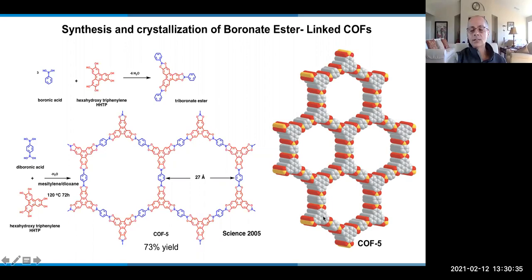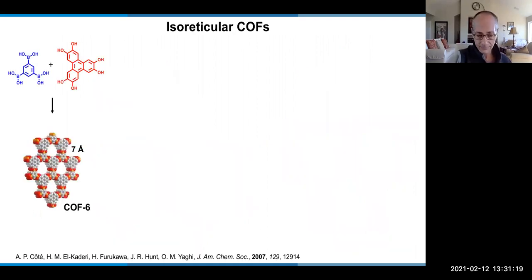And this reminds me to mention that when you're looking at 2D infinite COF structures, the stacking of the layers becomes an issue. That's where you find a lot of disorder. That turns out to be one of the important, let's say, characterization challenges with 2D COFs, is that you know the structure within the layer, but between the layers, how they stack sometimes is highly disordered, and it requires a lot of different refinement, trial and error to actually decipher, if at all, decipher the disorder. But that's an intrinsic challenge in characterizing the 2D COFs, and it's an ongoing study.